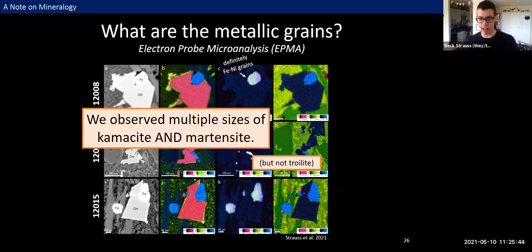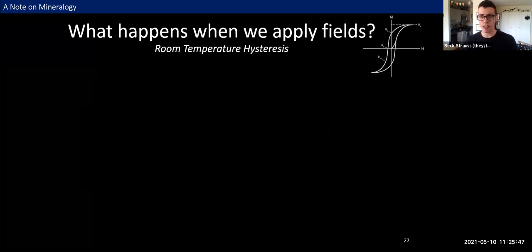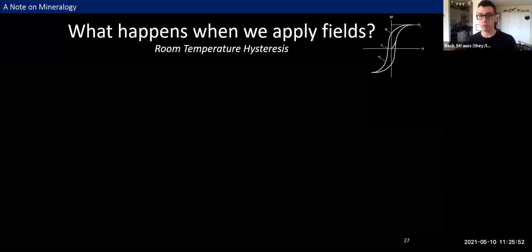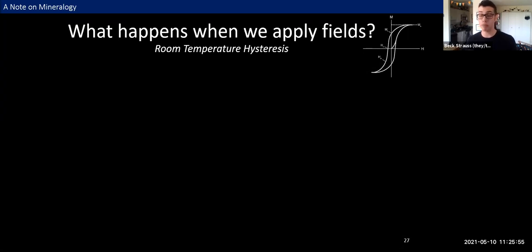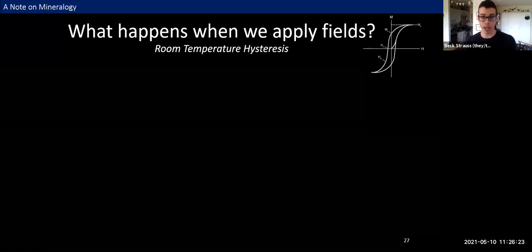Okay, so then we asked, what happens when we apply fields to these samples? And we did a series of room temperature hysteresis experiments, which are kind of a bread and butter technique for rock magnetism and have been so for more than 50 years. In a hysteresis experiment, we are applying a magnetic field under controlled conditions and measuring magnetization as it's applied. So we apply a field that increases in intensity in some positive direction, return that field to zero, apply the same intensity of field in the opposite direction, and then return to zero. And we track changes in magnetization as that happens, knowing that ferromagnetic materials respond in a very particular way here.